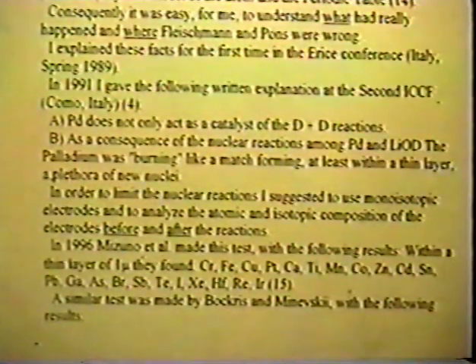A, palladium does not only act as a catalyst of the deuterium plus deuterium reactions. B, as a consequence of the nuclear reactions among Pd and LiOD, the palladium was burning like a match, forming at least within a thin layer a plethora of new nuclei. And this apparently is what other people are now talking about. In order to limit the nuclear reactions, I suggested to use monoisotopic electrodes and to analyze the atomic and isotopic composition of the electrodes before and after the reactions.